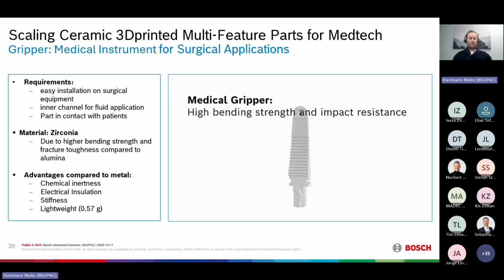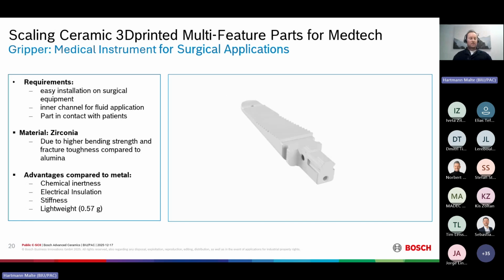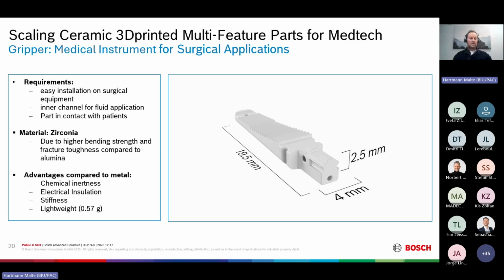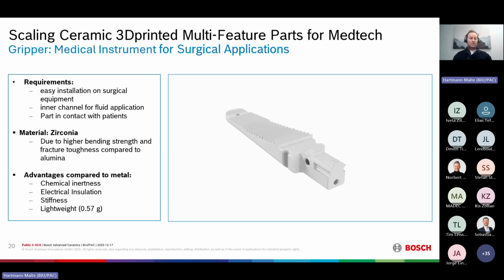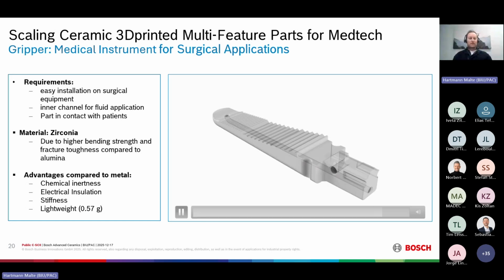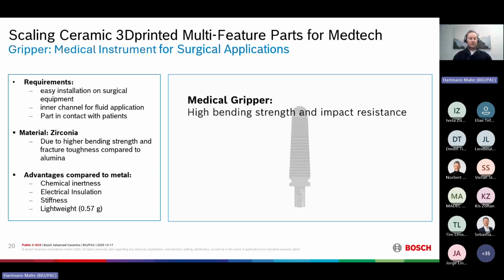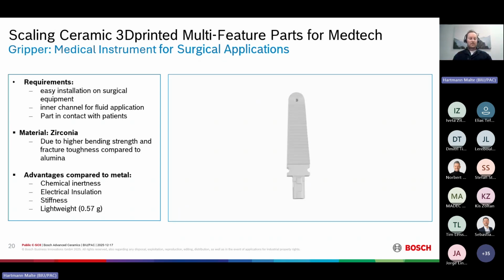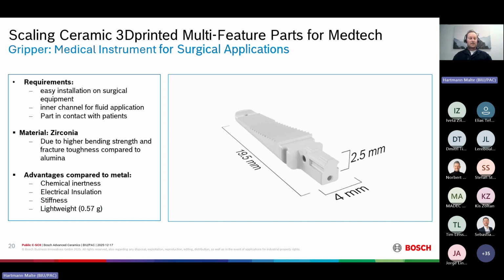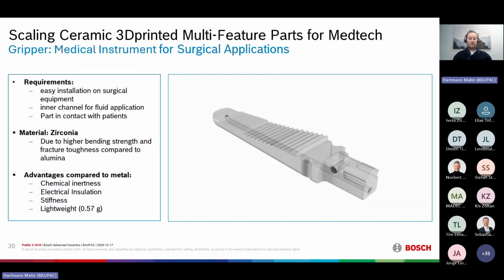Our suggestion for this part was zirconia as the material, and therefore it is also produced in that material type due to its higher bending strength and fracture toughness compared to alumina. Several advantages compared to metal exist, and those are chemical inertness, electrical insulation, the stiffness, and, not to be underestimated, the light weight of this part. So this only weighs 0.57 grams.